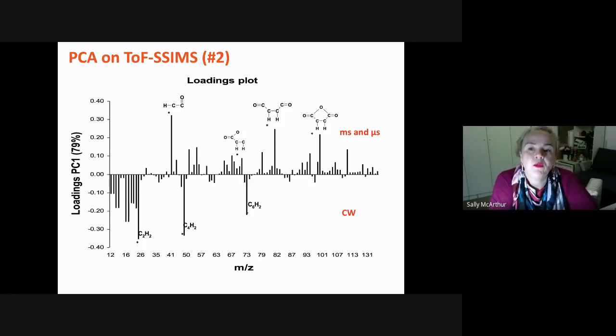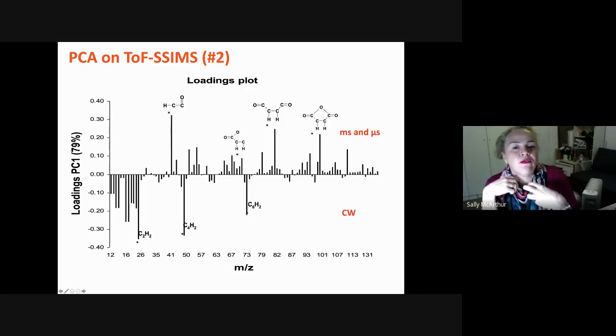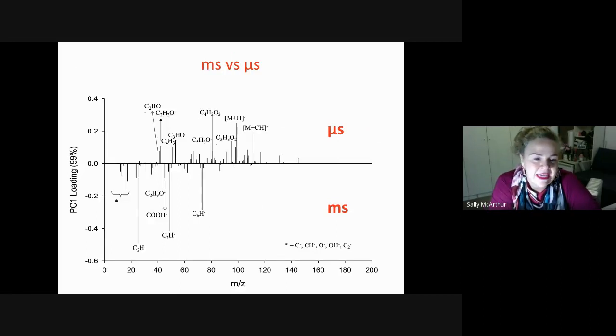And when we look at the loadings plot, we can start to see that if we just compare continuous wave to the millisecond and the microsecond, they split, and you can see the actual components of the system that are making it up. So we've got some ring opening and different features, and that unsurprisingly groups the microsecond and the millisecond data together compared to the hydrocarbon species that are more prevalent. These are the peaks that cause differences between the spectra, not the peaks that are the same. But if we then just look at the microsecond and the millisecond, you can start to see why that fluorine reactivity was different, because it's the microsecond plasma polymers that actually contain the reactive monomer that is present, and the anhydride groups in the surface as well.